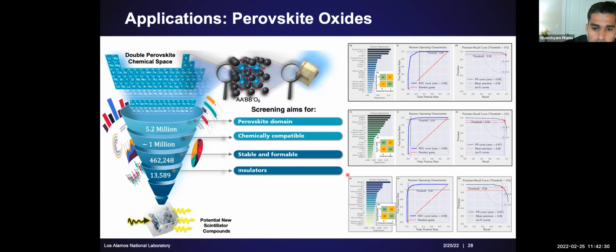And so before building a regression model for band gap prediction, we first separate the wide band gap and small band gap materials. So everything below 0.5 eV DFT band gap and metals are separated, and we only consider for our regression model compounds with DFT PBE band gaps greater than 0.5.